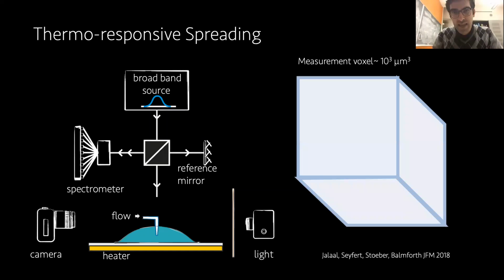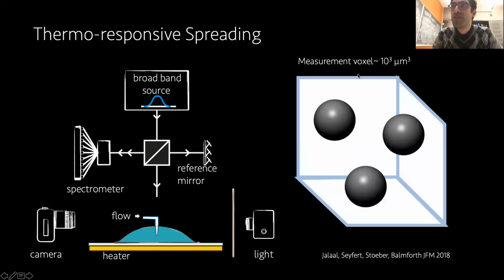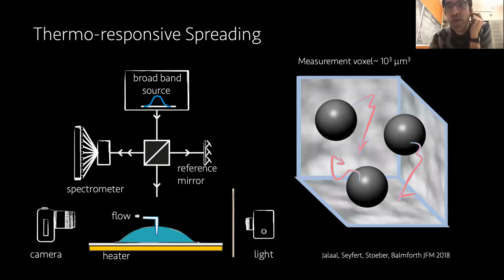Okay, what we did is we made a little bit of modification, and we tried to do some sort of microrheology. So we added microparticles to our thermoresponsive polymers like this. The measurement voxel of this experimental technique is around 10 to the power 3 micrometer cubed, and we put smaller particles inside it. What these smaller particles do, when they do Brownian motion, they do local light interference, which results in these so-called speckle patterns. If they are in a gel, they're trapped or caged in the polymeric matrix, so they don't do Brownian motion. But if they are in a Newtonian phase, they do Brownian motion. So that was the idea.